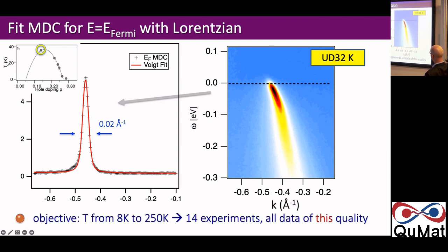So this is one single energy. Now we can move this dashed line down and slice and slice and slice our data and refit it each time, right? So we have many, many frequencies. The steps in frequency are 3 millivolts. So we've got hundreds of spectra going down in energy. And this is one particular doping level, and this was measured at 8 Kelvin. With other ones, we're going to measure at 8 Kelvin, 25 Kelvin, 60, 80, upwards, something like 14 experiments, a function of temperature.